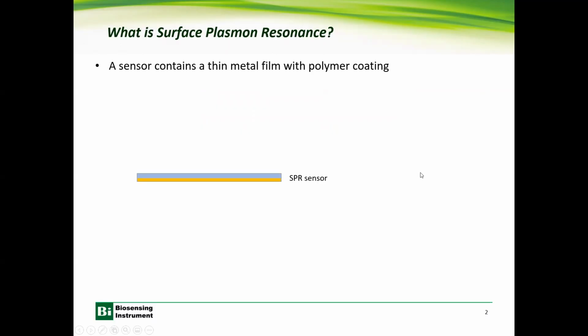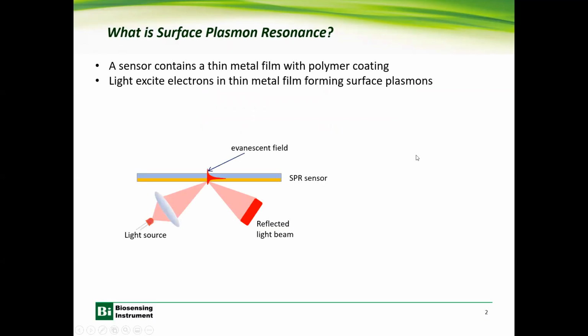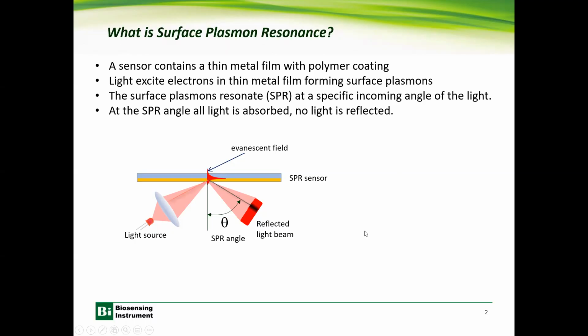So, surface plasmon resonance. The surface plasmons are the electromagnetic wave resonances trapped at the interface between the metal conductor and the insulator. When you shine a laser to the interface at a certain angle, all the light will be reflected. And when you change the angle, at some angles the incident laser will start to resonate with the surface plasmon. In that case, all the incident light energy will be absorbed by the surface plasmon, and therefore the reflected light will become very low or become zero.